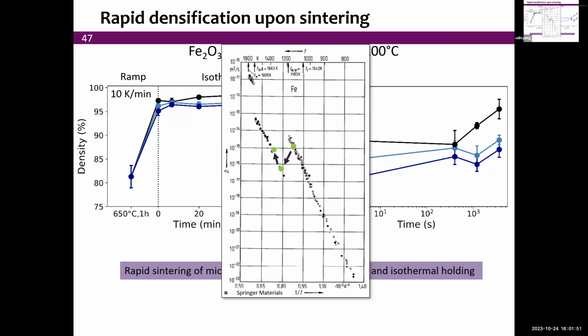only when you're back to 1,100 degrees C do you retrieve your equivalent diffusion coefficient, which explains why we're losing sintering efficiency as we increase temperature from one phase to the other. So that makes sense, and once we understand this, you may as well sinter at relatively low temperatures while taking full benefit of the open, fast diffusing BCC structure.